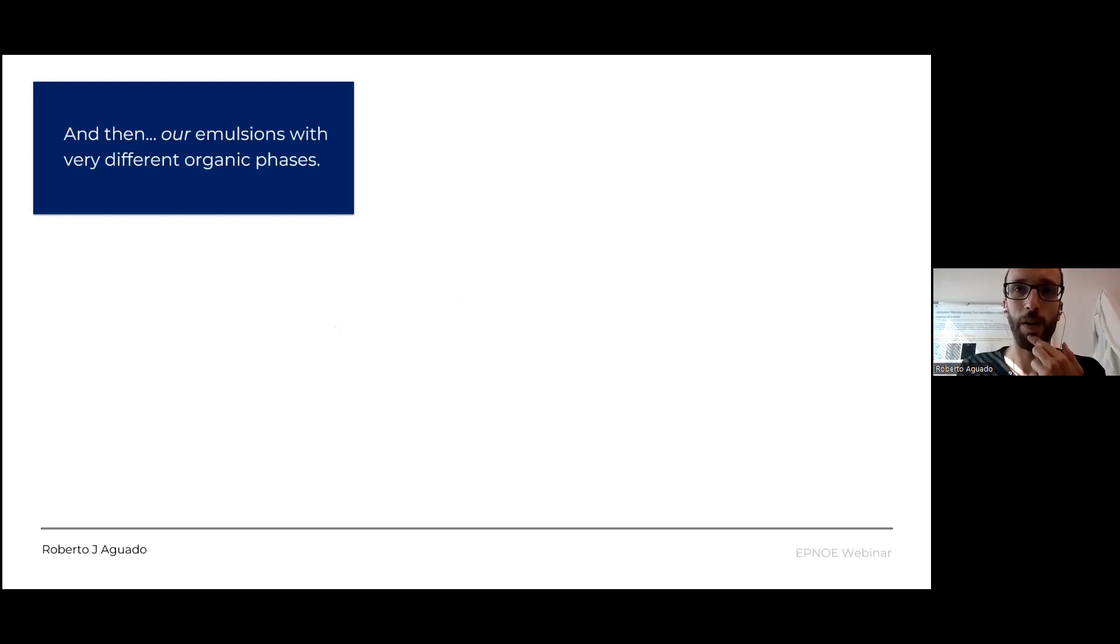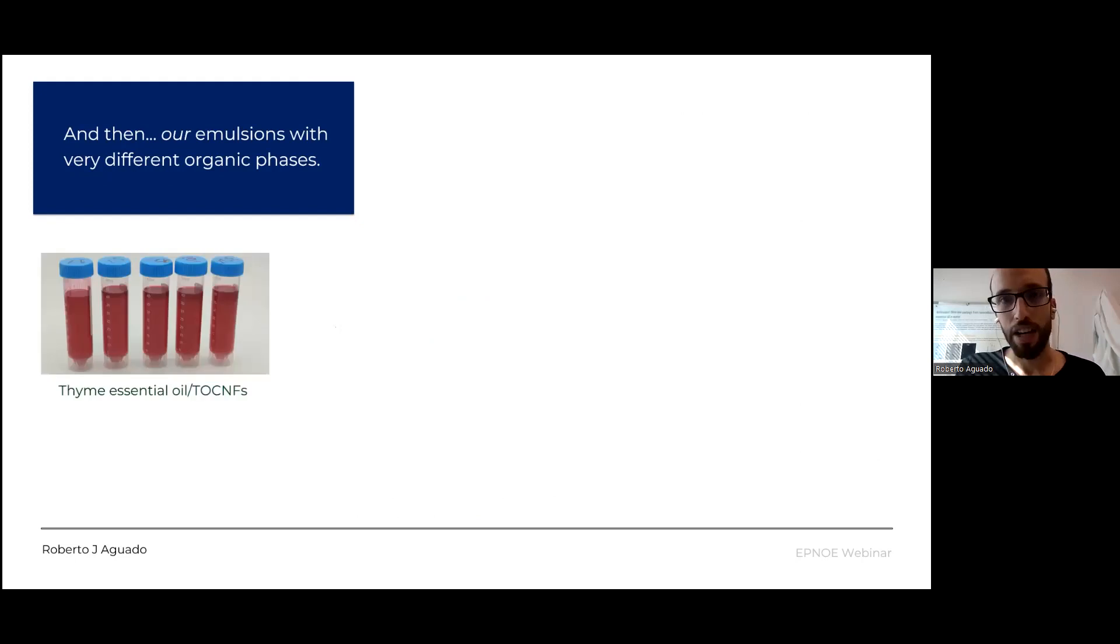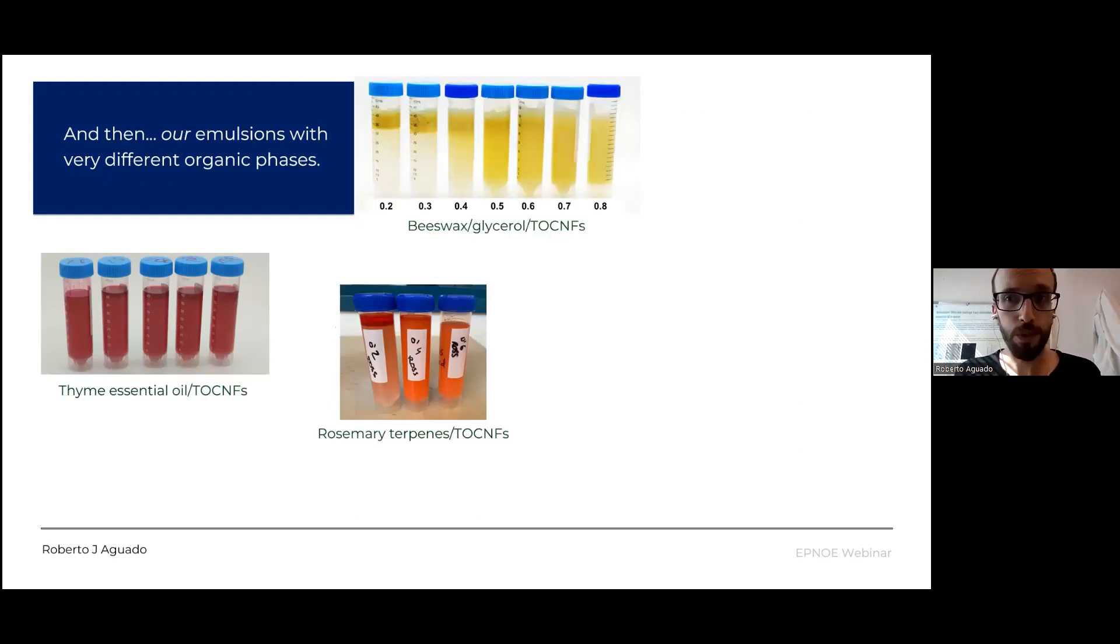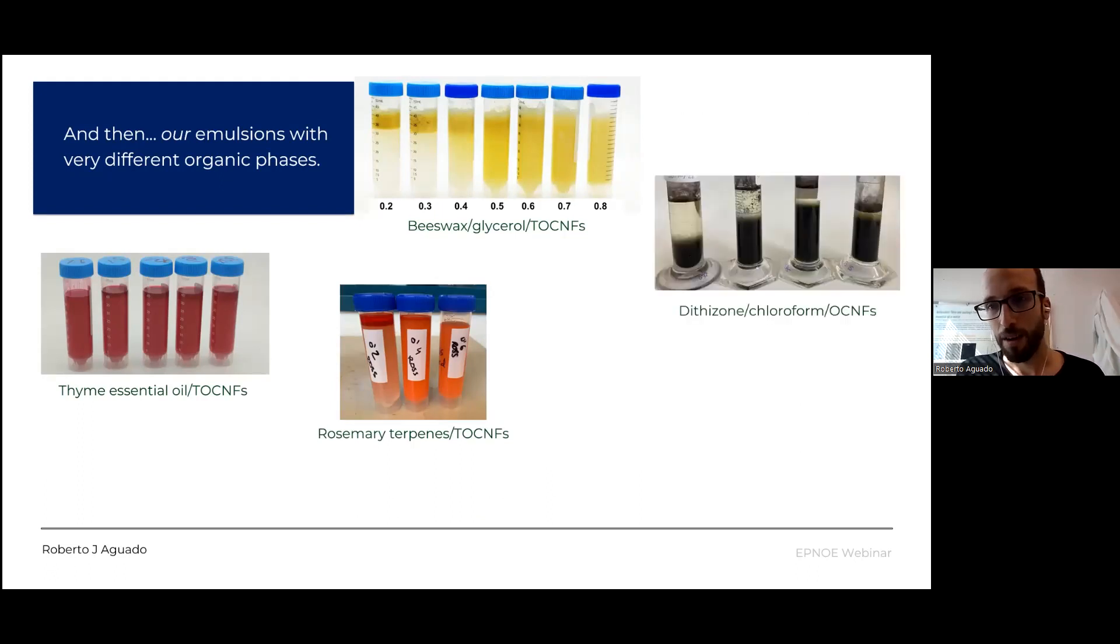So now let's get into our recent work, because all of this has been started in 2022. We have been able to stabilize with TEMPO oxidized nanofibers and even oxalic oxidized nanofibers a lot of different organic phases: thyme essential oil, mostly hydrophobic, even more hydrophobic rosemary terpenes, beeswax which is solid at room temperature. So that's entering the realm of suspensions with the Pickering suspension or Ramsden suspensions.